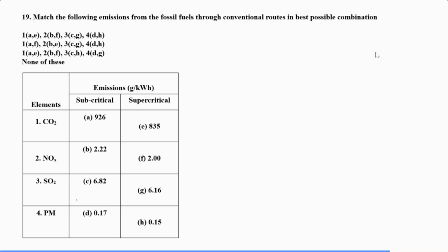To reduce them, if we perform the combustion in the subcritical state, the emission amount is this, in gram per kilowatt hour. But in supercritical we can see that these emissions are reduced. What is desirable is that we shift to supercritical, which is not yet practiced, but if we shift to supercritical condition, then the emission will decrease, which is desirable: 835 is less than 926, 2 is less than 2.22, 6.16 is less than 6.82, and 0.15 is less than 0.17. So the answer is they are correctly written: A to E, B to F, C to G, and D to H. So the answer is the first one.